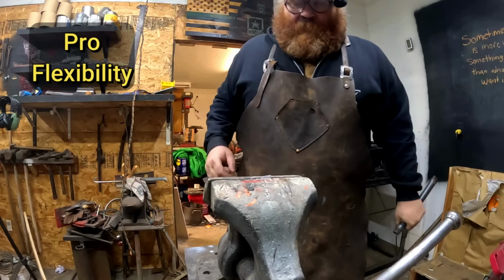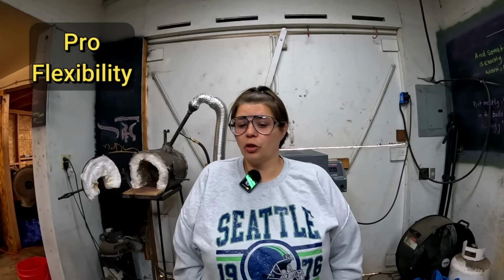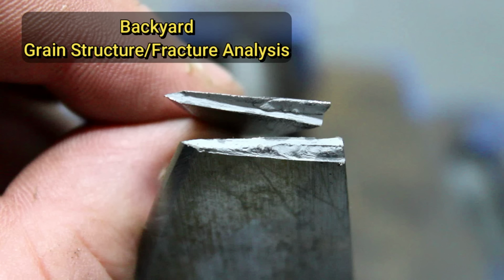Oh, wow. Holy sh! It broke into 3 pieces. The temper on the backyard heat treat is what really surprised me. I was confident in the quench, but the temper was really the question. I didn't clean the blade before tempering, which is a bad habit of mine. And if I had, I could have read the temper colors and controlled it a little better. What actually happened is I basically nailed the temper in the middle of the blade, but held back too much on the tip, trying not to overheat it.